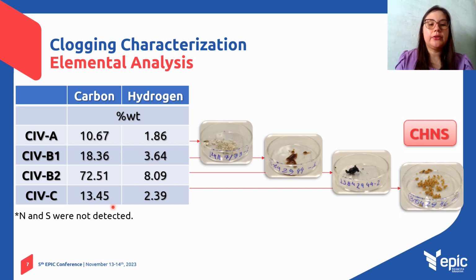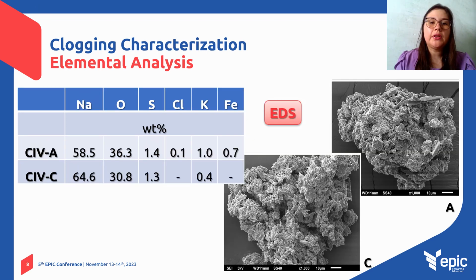And we detected 2 natures of the clogging material samples, where the organic sample is rich in carbon, and the inorganic samples are not rich in carbon, which explains the solubility of the organic samples in toluene and the solubility of the inorganic samples in water. The micrographs obtained from scanning electron microscopy showed not a regular crystalline structure of the clogging materials from chemical injection valves A and C. Interestingly, the energy dispersive spectroscopy analysis revealed a great amount of sodium in the inorganic samples A and C.